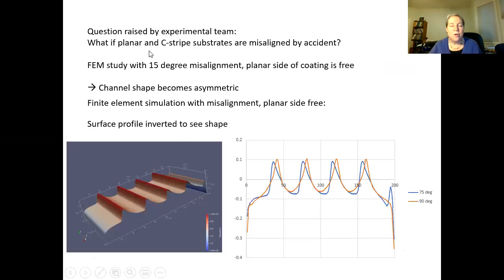And then the question is, okay, so Greta Babakhanova asks, when I put those two pieces together, what if I accidentally misaligned them? And it's like, well, we can do this simulation. And so we misaligned them by 15 degrees. And what we found was, then your channels become asymmetric. And so this is actually the channels turned upside down, so they look like shark fins. And so, there's a symmetric case and there's an asymmetric case. So sure, if you misalign the two faces, that's one reason why they might be asymmetric.